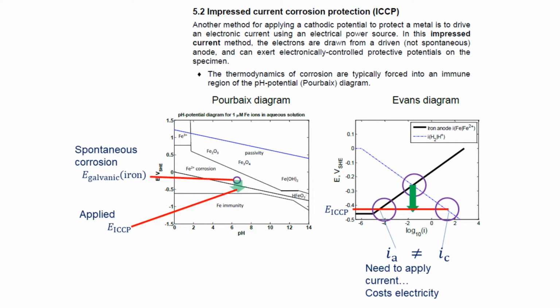This means there are some comments we can immediately make about the best way to operate a cathodic protection system like this. A comment is that we should be looking to decrease the surface potential of the metal to be protected, in this case the iron, maybe close to the boundary between immunity and the start of active corrosion. That means there's going to be a pretty negligible rate of corrosion.